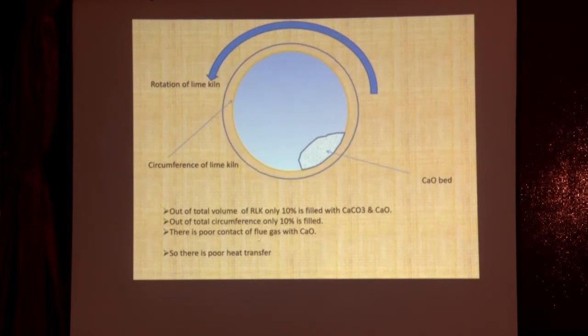There is poor contact between flue gas and CaO. There is also a poor heat transfer coefficient, because most of the heat is lost through the surface area of the rotary lime kiln as well as in the flue gases, to dry the lime bed. On average, people have dryness of 60%. Those who are very good, with very low silica, are achieving dryness up to 75%, even 80%. They have optimized their fuel consumption up to 160 kg per ton of CaO.